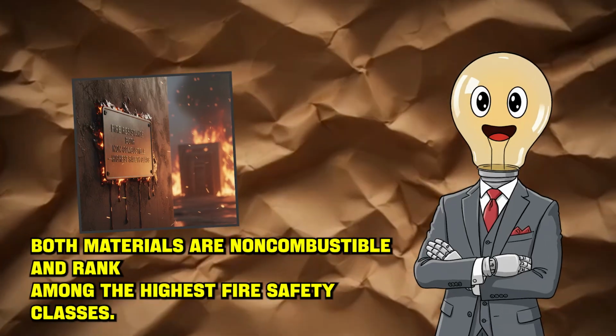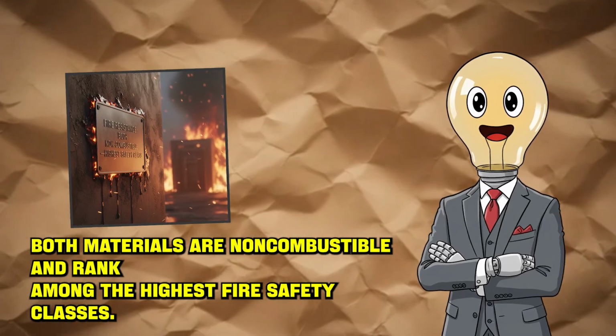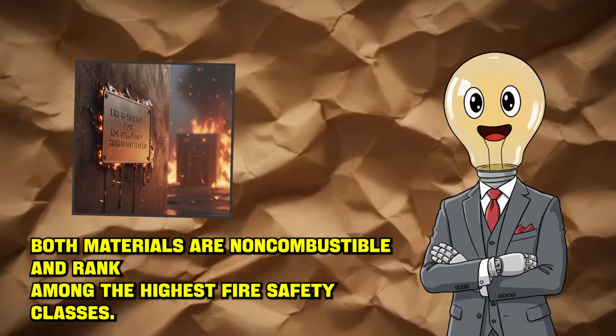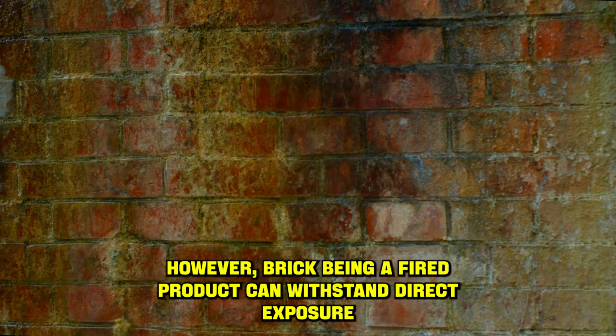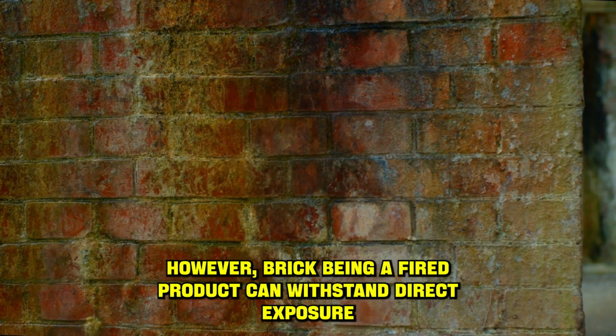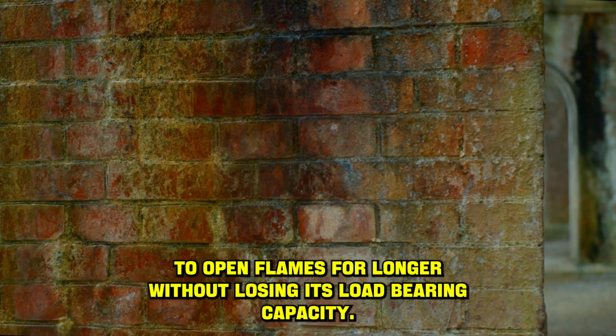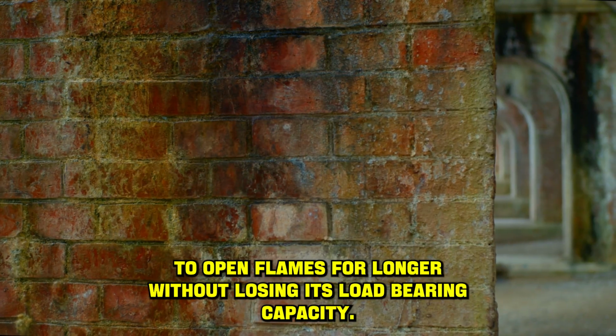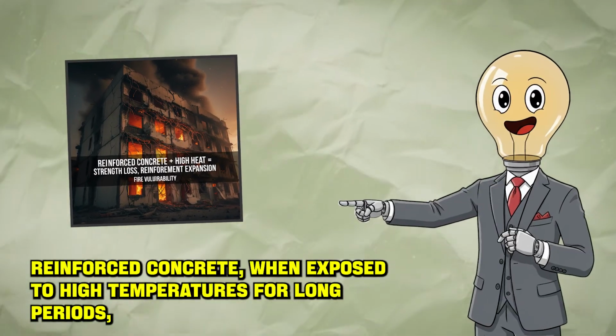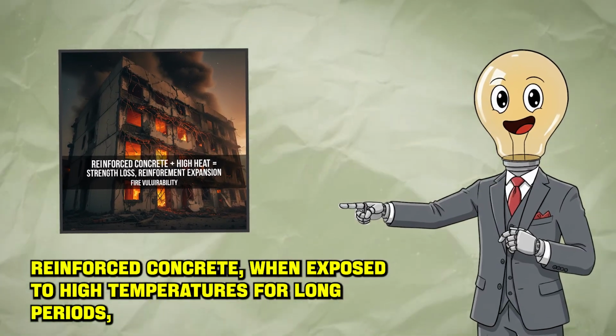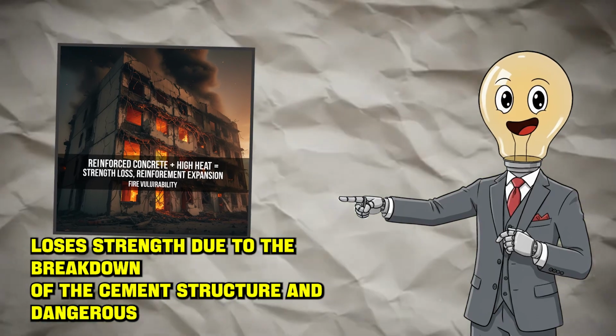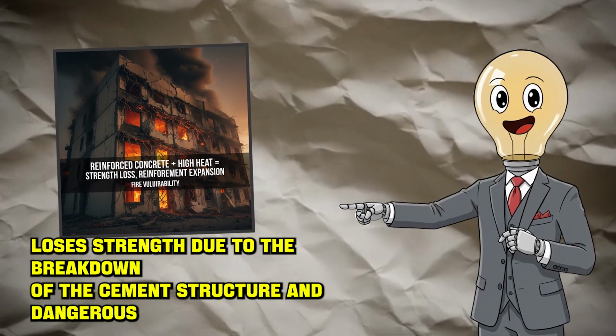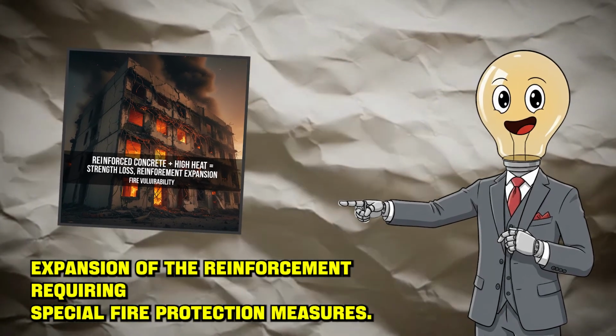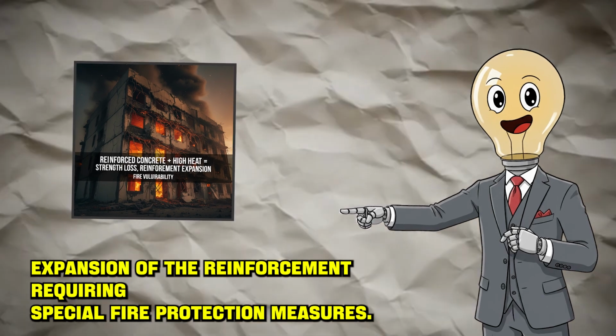Fire resistance. Both materials are non-combustible and rank among the highest fire safety classes. However, brick, being a fired product, can withstand direct exposure to open flames for longer without losing its load-bearing capacity. Reinforced concrete, when exposed to high temperatures for long periods, loses strength due to the breakdown of the cement structure and dangerous expansion of the reinforcement, requiring special fire protection measures.